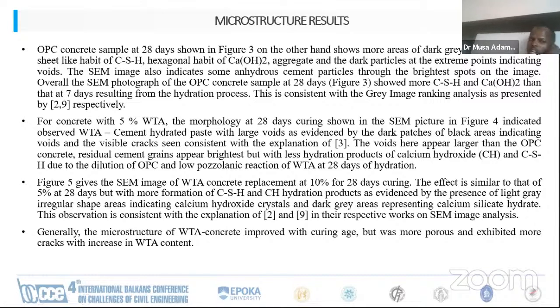Then for concrete with 5% WTA, the morphology at 28 days curing, shown in figure 4, indicated WTA cement hydrated paste with large voids, as evidenced by the dark patches of black areas indicating voids and the visible crack, seen consistent with the explanation.